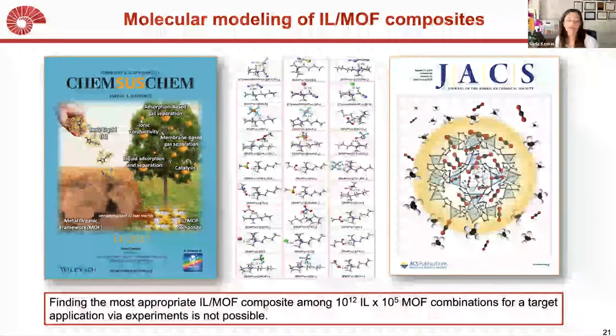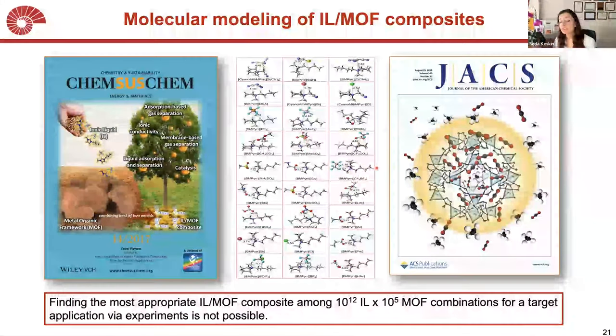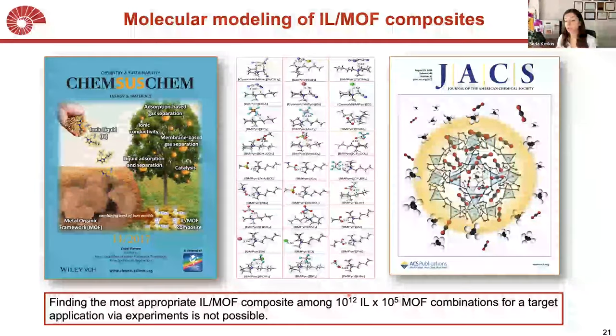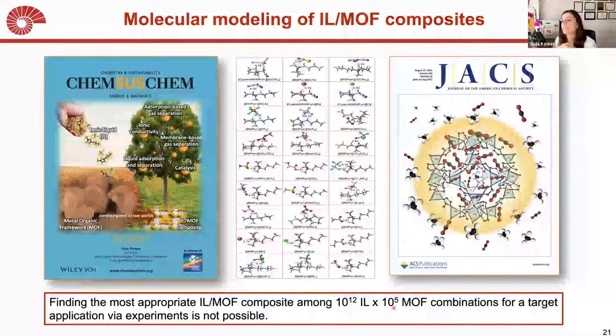This is what we did in the last 6 years. But the question is, I have 10 to the power 12 different types of ionic liquids, millions of MOFs. So we don't know how to choose the best combination of ionic liquid and MOF to make these experiments. We reported several different composites, but actually we did all of them by trial and error. We were just trying different ionic liquids with different MOFs. And if we got a good separation performance, we were publishing it. If not, we were continuing to find a new material, purely by trial and error.